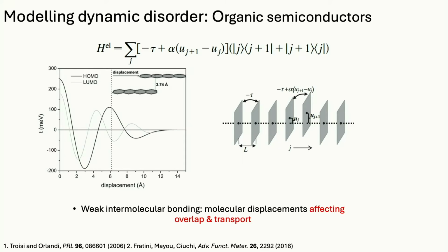Okay, so now I want to tell you the message of what's happening with all this dynamical motion. What I want you to think about is these hybrid perovskites. If you do X-ray diffraction, you'll say, yep, it's a cubic crystal, looks normal to me. But if you look on a picosecond by picosecond, or even maybe 100 picoseconds, different parts of the material are doing very different things. So how can we start to analyze that? Because when you look at a time-independent measurement like X-ray, it's all hidden.